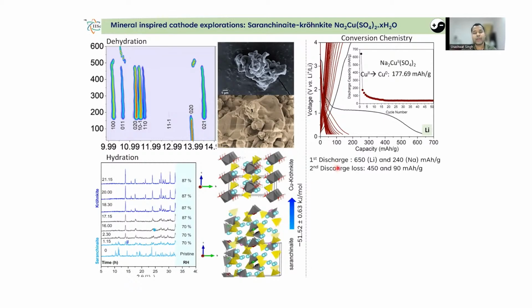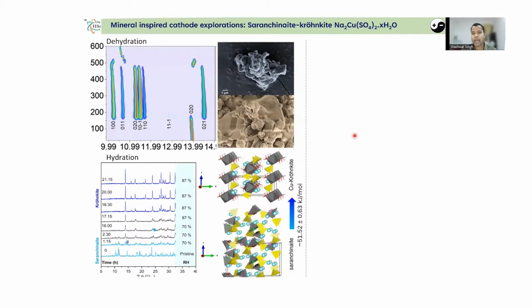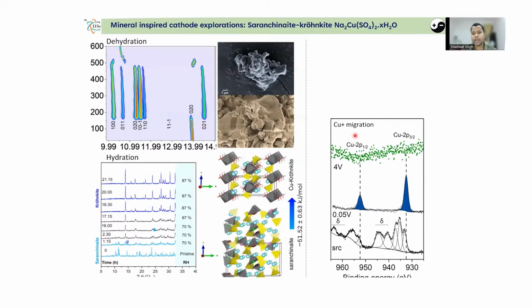However, conversion-based chemistry is possible in a copper-based system, and therefore we took this compound to a very low voltage to see if conversion chemistry based energy storage can be done. The first discharge capacity is quite high. However, further optimization is needed to get any meaningful energy storage in this compound. The cause of irreversibility is probably copper ion migration, either into the electrolyte or to the lithium side.